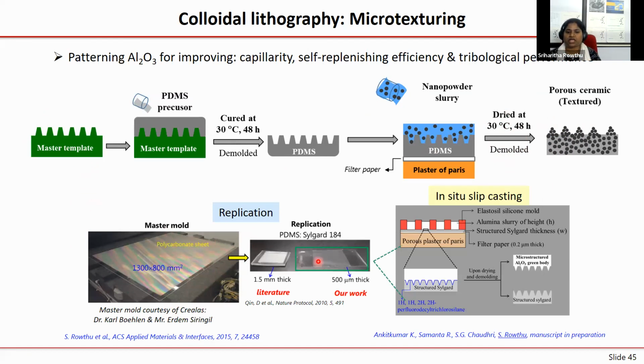Now this is how the PDMS replicas look like in the literature. Until my work, people always used very thick PDMS, around 1.5, 2 or 3 mm thickness. But in my study, I came up and said, not just like that, there was a scientific reasoning, let's go for a thinner PDMS, because this is going to help in the better drying process of your ceramics.